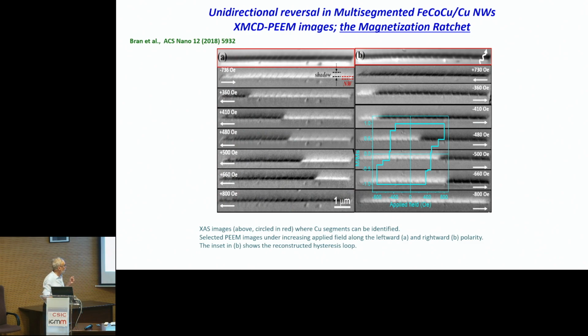magnetic segments. But if we start with the opposite saturation on the positive field and we apply a negative field, again we observe the reversal of magnetization starting from the same end. So this is why we call it ratchet, magnetization ratchet, because reversal starts always from the same end. So it is possible to reconstruct the hysteresis loop of this nanowire with this experiment.